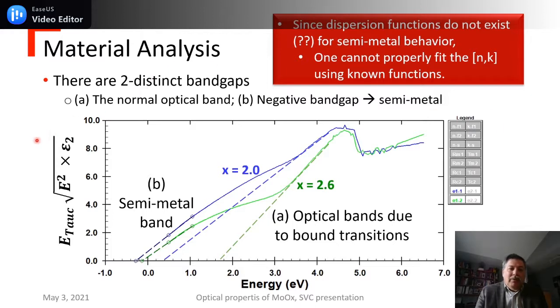If any of you have ever looked at the Tauc method for the band gap, it usually involves, rather than the imaginary part of the dielectric function, alpha. The problem is, alpha depends only on K, the extinction coefficient, and assumes that N, the refractive index, is constant, which is never true. So I encourage you to stop using alpha if you make band gap calculations like this.